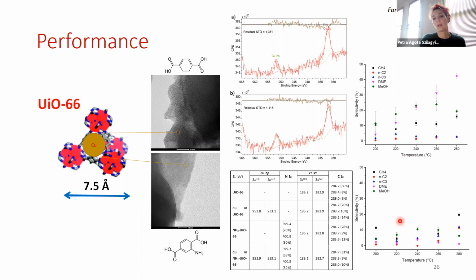Basically, the amino UiO-66 matrix embedding copper was not active at all. Whereas in the case of the pristine UiO-66, we didn't observe a lot of methanol, but what we observed is that the methanol was etherized, and there was a condensation reaction, and the main product was dimethyl ether. And that we could associate with the presence of the acid sites in the inorganic nodes of the UiO-66.